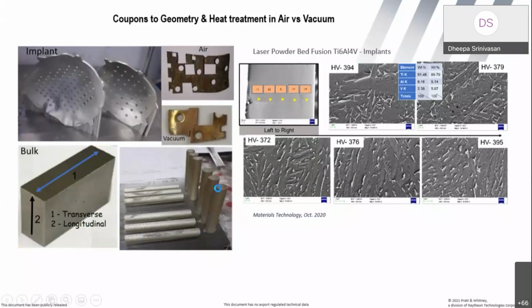And these are cylinders in two different orientations. Namely, you've got a transverse orientation and a longitudinal orientation for doing mechanical testing. However, what implication, I spoke to you about the mechanical property and the differences it can have between the bulk, within quotes, bulk vis-a-vis the part thickness. Here, what I'm highlighting is the importance of heat treatment in differentiating between the bulk and the actual part.